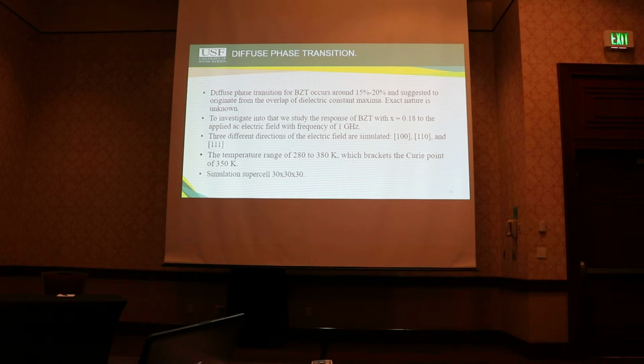So to investigate this, we took BZT at a concentration of 18% and applied an AC electric field at 1 gigahertz to it along 3 different directions: the 100, the 110, and the 111. And we used a temperature range of 280 to 380 Kelvin, as this nicely surrounds the Curie point of BZT of 350 Kelvin. And a supercell size of 30 by 30 by 30 is continued to be used.